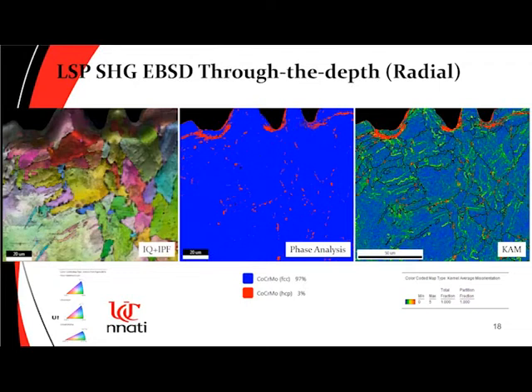Looking into the depth of one of the samples using EBSD, the phase analysis shows that a fraction of the surface has transformed from FCC to HCP and into a shallow distance in the material. In addition, the KAM maps show the high magnitude of misorientation at the surface due to the plastic deformation from LSP, which coincides with the areas of the phase transformation.